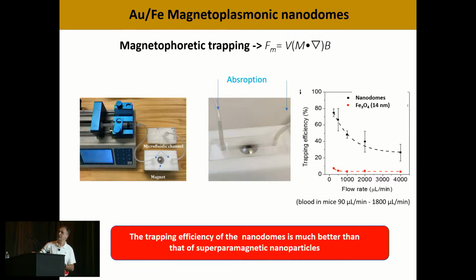speeds. And then you can see here that in a single run, using nanodomes, we can trap almost 80% of the domes in a single run using this structure. And when we increase the speed of the fluid, then the trapping goes down, but still it remains around 30% even for very high fluid speeds. Note that the blood in mice runs from 90 microliters per minute to 1800 microliters per minute. So this is faster than what the blood would run.